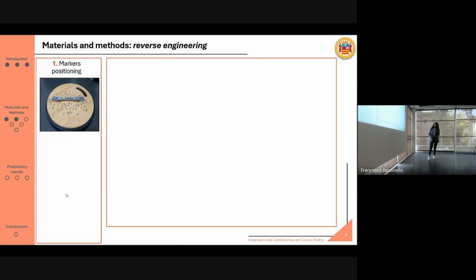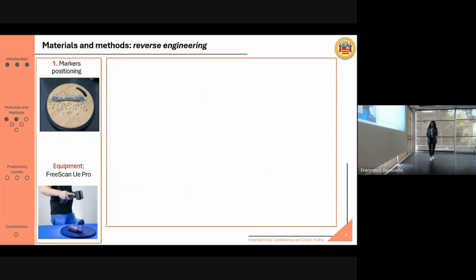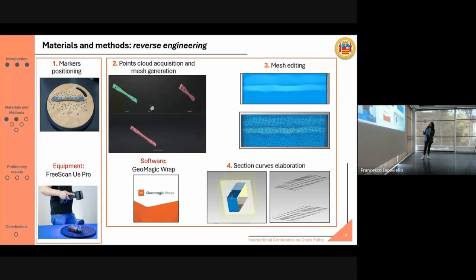each specimen was equipped with given markers. The specimens were positioned on a plate that was equipped with markers as well. Then we used a laser scanner, the FreeScan UE Pro, which is a small and portable scanner, quite easy to handle. And by scanning the specimens, we were able to acquire the point cloud. So we got this numerical model, which needed to be adjusted because there were some holes due to the presence of markers.